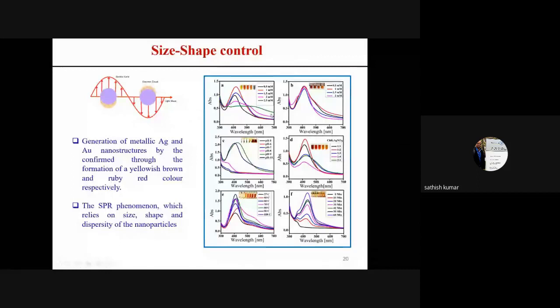As I mentioned earlier, in the synthesis of metal nanoparticles, not only the reducing agent and stabilizing agent play a role. Here we have optimized all the parameters like the quantity of reducing agent, the quantity of precursor, that is silver nitrate or gold chloride, based on the nanomaterial. Also the pH of the reaction medium. And another important parameter is the stoichiometric proportion of the reaction mixture, and the temperature and the incubation time, that is the reaction time. These parameters largely influence the size and the shape of the nanomaterials.